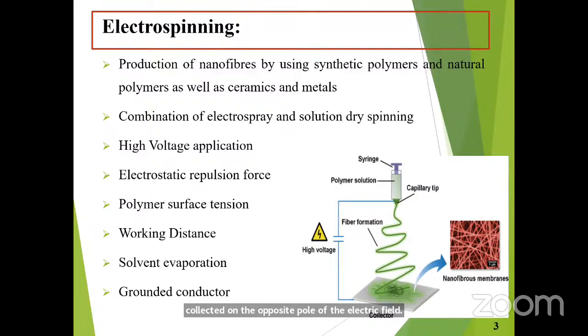During this, the traveling distance from the tip to the collector enables the solvent to evaporate due to the bending and stretching of the polymer. According to the basic principle, the electrospinning setup consists of three main parts. One, a high voltage source. Second, a syringe-based spinneret for polymer feeding having a metallic needle tip, and a collector, which should be a grounded conductor.